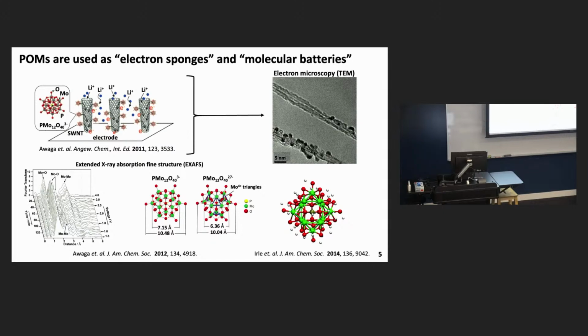Previous work showed that you can take these species and immobilize them on something like a carbon nanotube electrode. If you take an electron micrograph of such a material, you see something like this, where your carbon nanotubes are coated with the polyoxometalates. What's particularly interesting, though, is that these species can be cycled between different charge states, all the way from 3- up to 27-. So 24 electrons can be packed into something that's around 0.5 nanometer in size. So clearly, this is quite a lot of energy density that's useful for storage in supercapacitors.